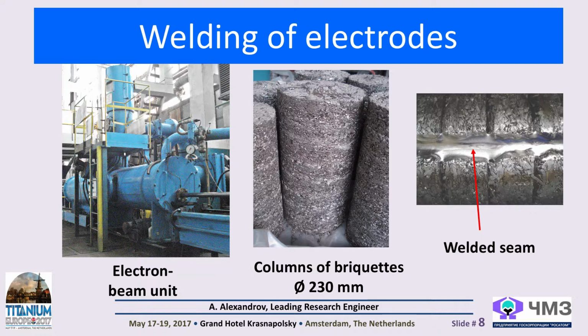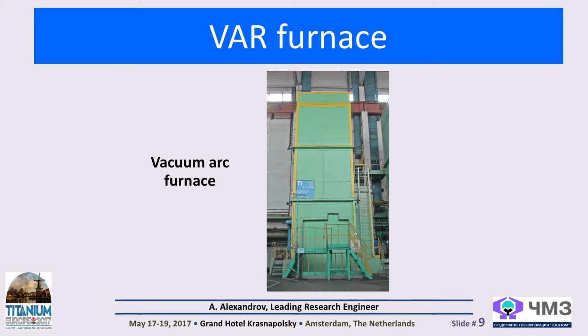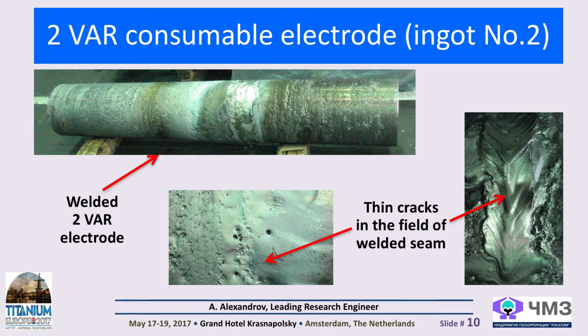The subsequent consumable electrodes of the second and third remeltings were welded with ring seams on the butted ends of ingots in vacuum units equipped with an electron beam thermocathode or electron gas discharge gun. There we met one more problem: high sensitivity of the material to thermal stresses, which is expressed in the formation of surface cracks. You can see them on the slide, on and around the places of locally melted metal. Some of the most dangerous cracks were welded a second time.